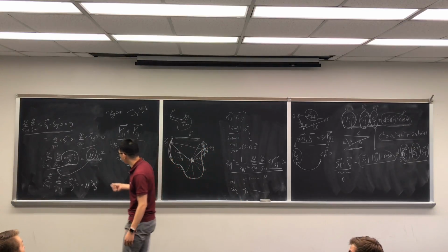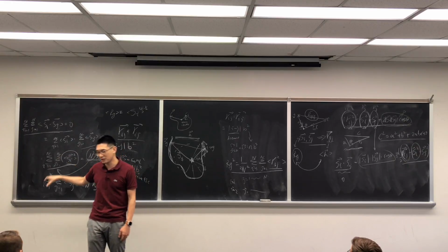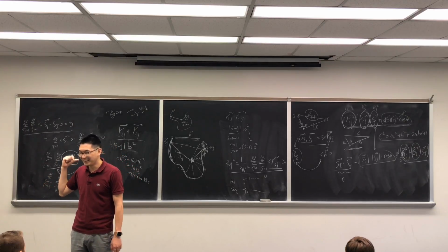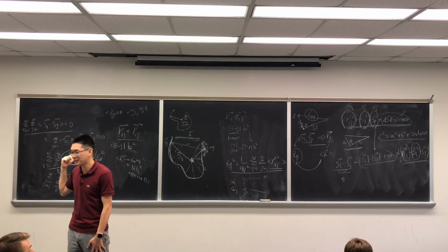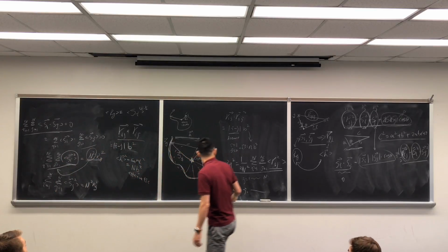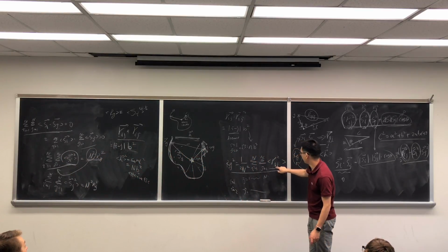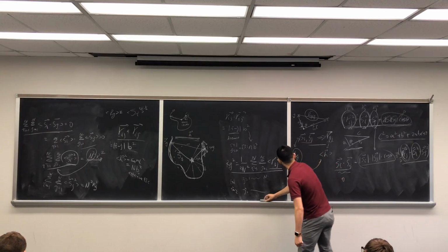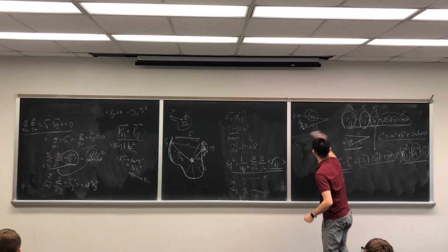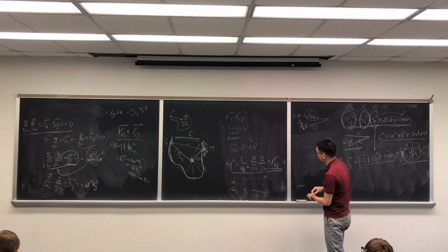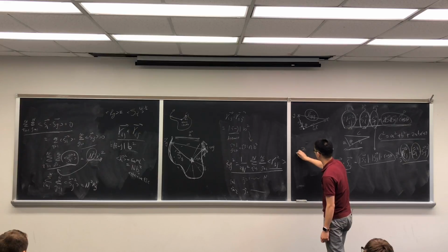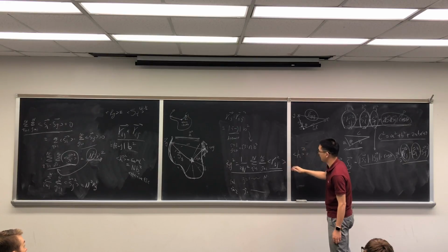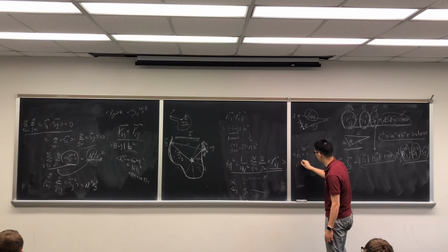And if you look at what I wrote at the beginning of class, why we care about Rg is that now you see the definition. Rg is equal to Rij, where i and j could be anything along the chain. While h squared is basically a special case where i equals 1 and j equals the last one.